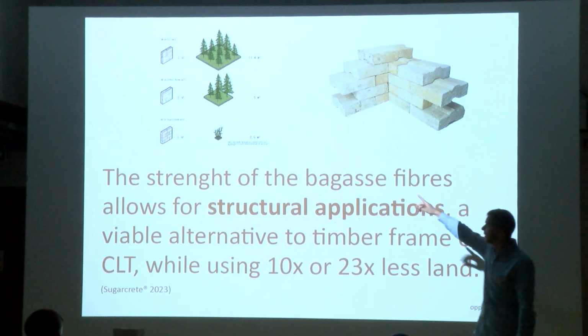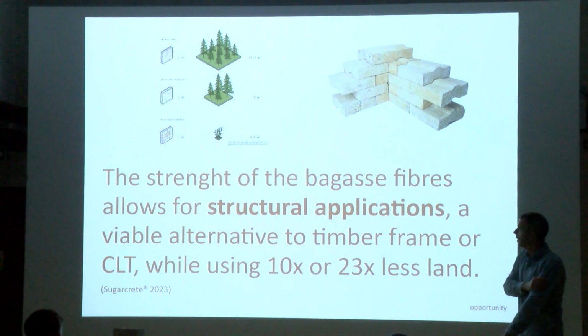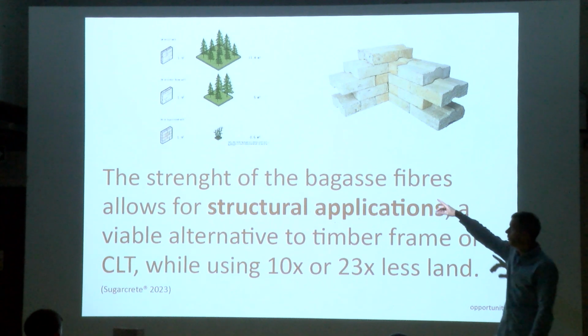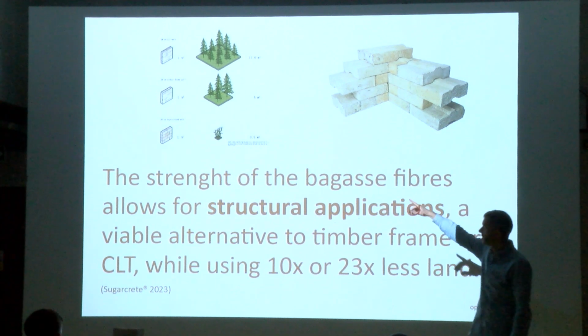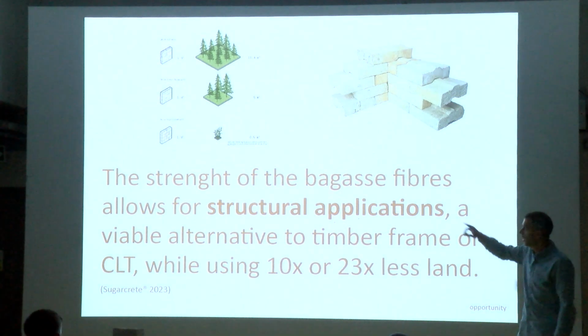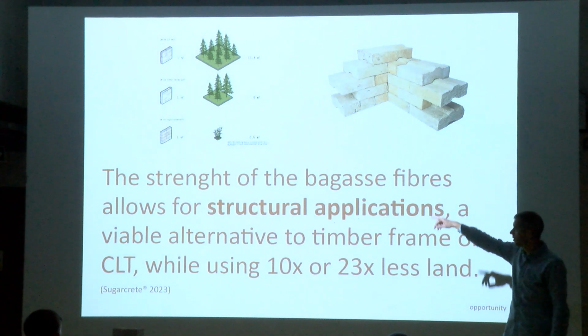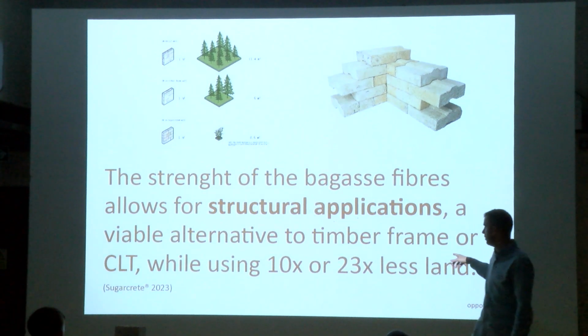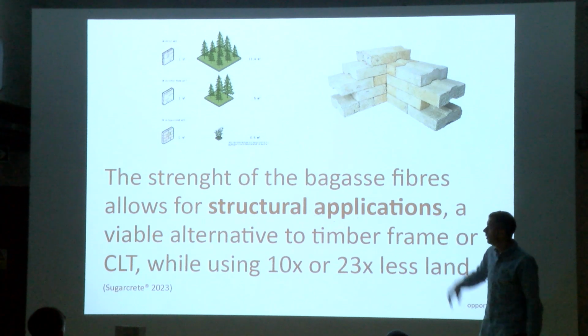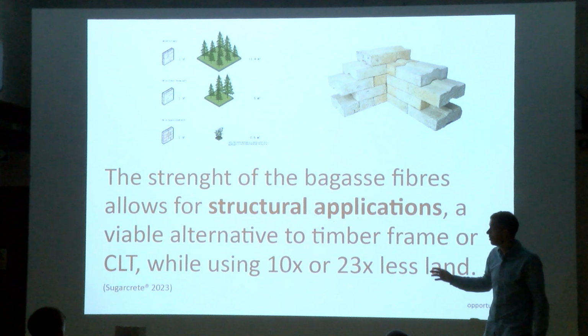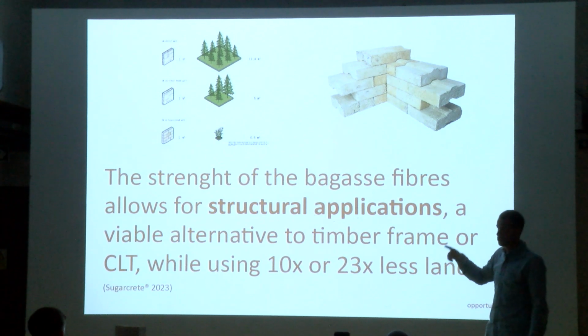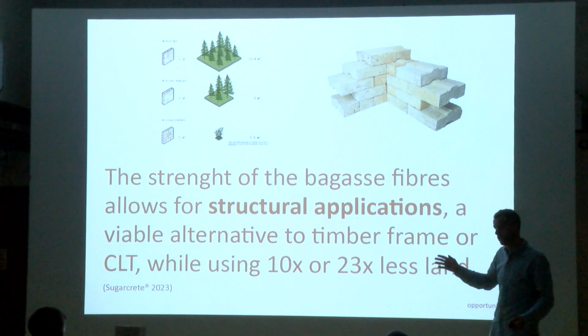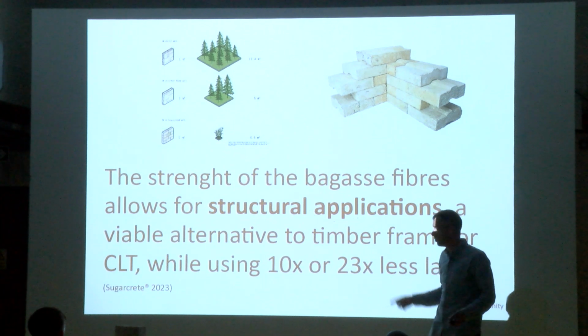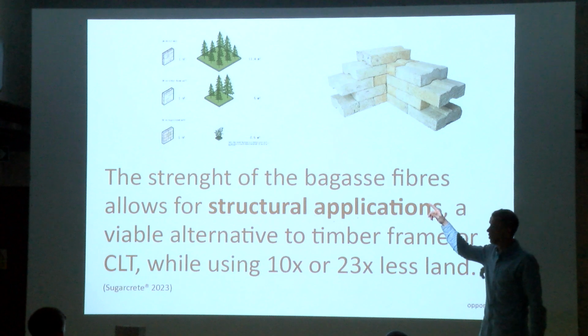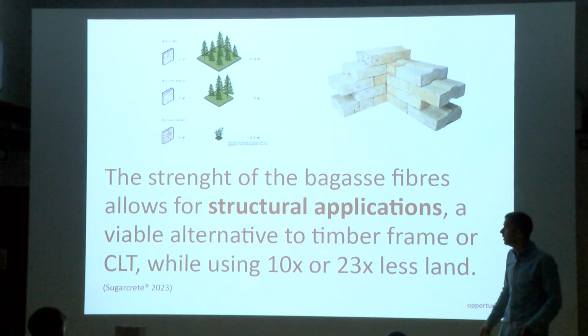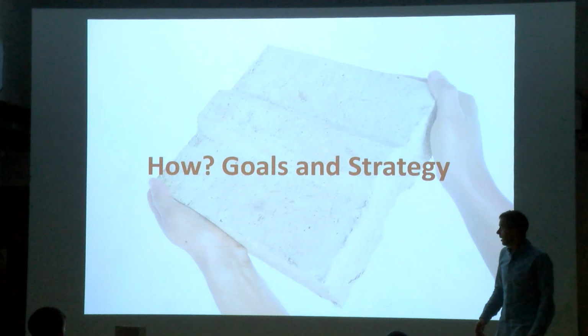So that's a study that we did, just comparing the amount of land that you need to create 1 square meter of CLT, 1 square meter of a timber frame wall, and 1 square meter of sugarcrete wall, and it's 10 times and 23 times less land required to create the same amount of construction. In a year, you grow a crop of sugarcane, normally seasonal. During 6 months they harvest, and then the other 6 months the plant is growing, whereas traditional forestry takes up to 50 years to be ready for harvesting.